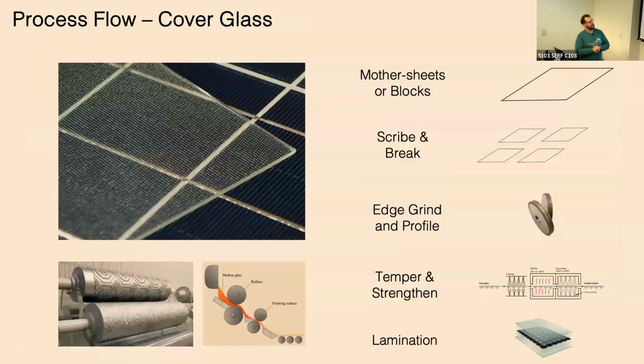But here's the breakdown, starting with my cartoons here. You start off with a big mother sheet or block of glass, and then you take a diamond, typically a diamond scribe. You scribe a line, snap a piece of glass into your fairly rough XY geometry, and then you edge grind profile it. If you're going to put on a pencil edge or a beveled edge, it'll go through that process to create the final perimeter shape. You go to thermal tempering or strengthening and then lamination.